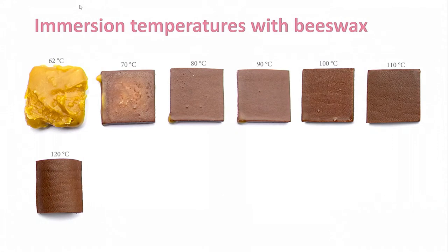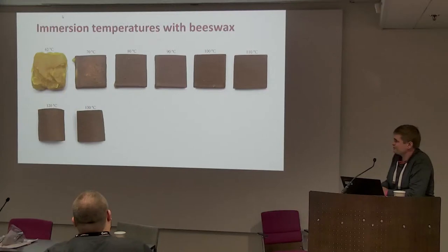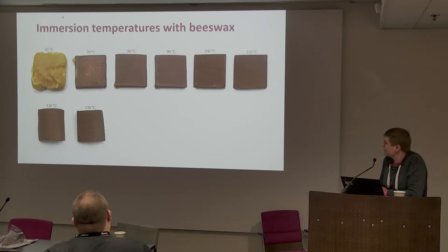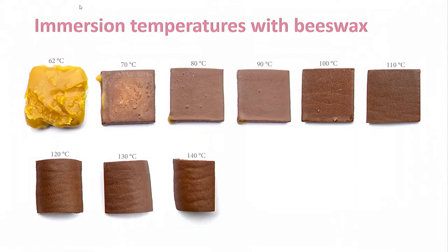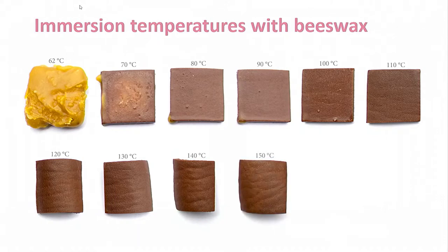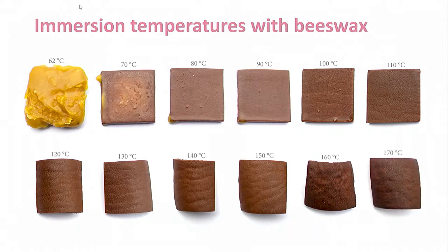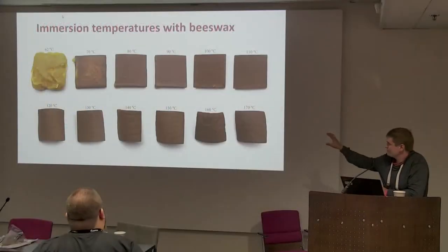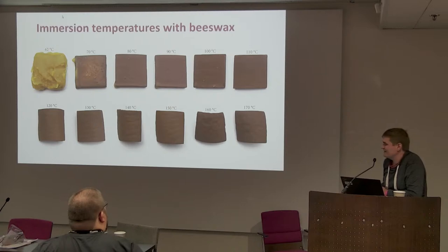And then at some point around 120, 130, you can see that these pieces have started to deform. These have all been exactly 1 minute at this temperature. At this point you can see that the pieces have been deformed, not in a catastrophic way. But if you want to be safe about it, around 100 degrees, once again, is the way to go. Mechanically speaking, maybe 120, 130 might be beneficial. After that, it starts deforming aggressively. And finally, at 160 and 170 degrees, we have a crumbled piece of leather. So do not go as high as that. That's not safe. I did it for science.